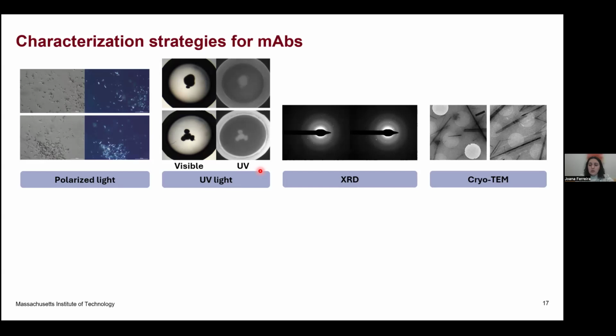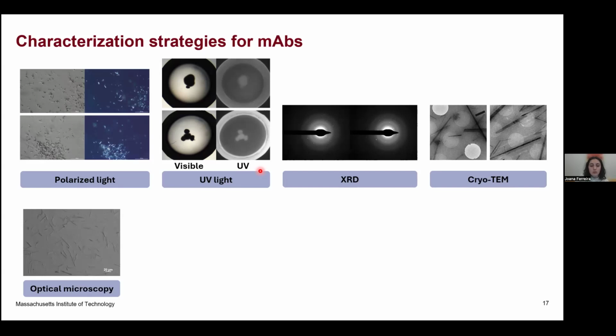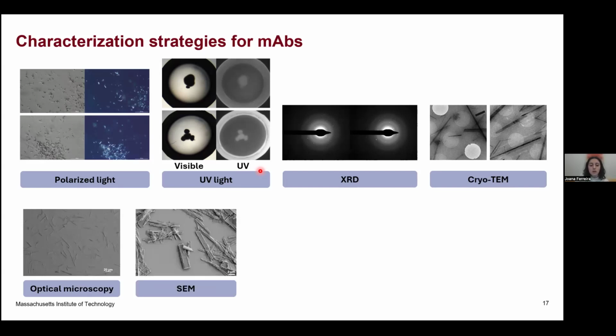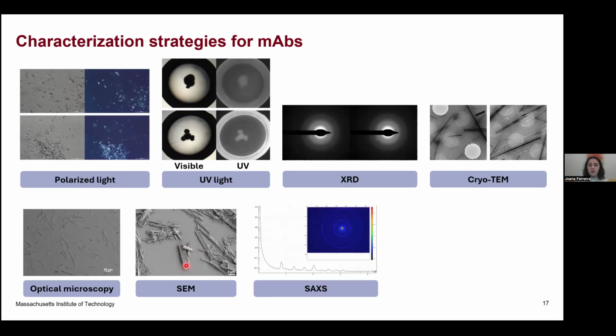We also tried the cryo-TEM to observe in a more clear way our needle-shaped crystals. Optical microscopy that we used a lot during our continuous runs. Then we also tried the SEM, because for some of the runs, we could see that besides these very needle-shaped crystals, we could also see some plates, and we wanted to take a further look. We also ran SAXS because in terms of material, we don't need a lot of material to run SAXS, and we were very successful.